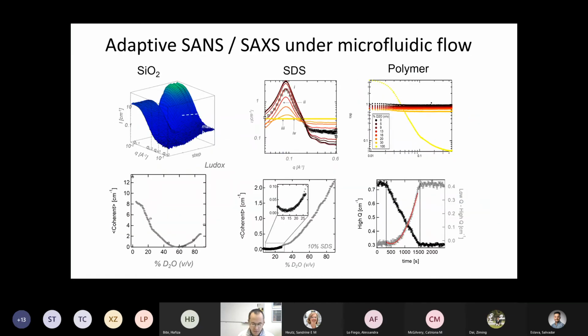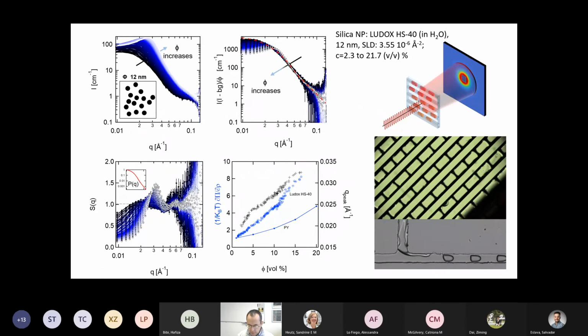Well, we've taken as model systems here some silica, some glass beads, if you wish, about 20 nanometers or so in size, some surfactants, because we often need to stabilize these excipients with the help of a surfactant, and a polymer, which is a Gaussian polymer, in this case, in solution. And as we evolve these as a function of concentration or time, we can look at the types of things that scatterers are interested in.